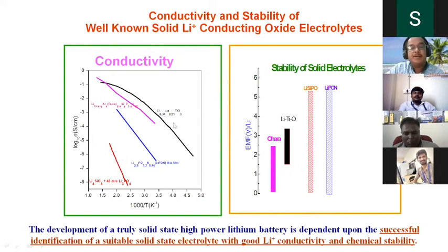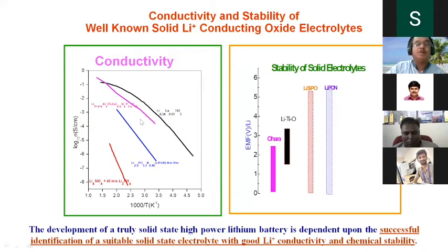The lithium titanate has the best conductivity, but the potential is 3 point something, and moreover, titanium is the biggest problem, so it's very difficult to have metallic lithium with titanium. Easily it can be reduced. And Ohara, this particle, people are working on this lithium, titanium, aluminum, germanium phosphates. This is also not so good.